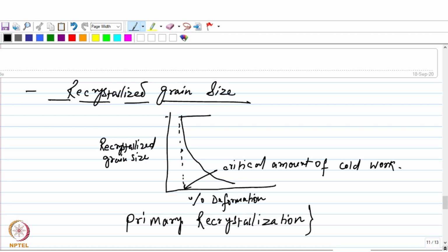But now, once these recrystallized grains have formed, if you continue to heat the material or hold it for a longer time, then what is going to happen? So there is still enough driving force for the boundaries to move and the grains to grow, because it will still try to reduce the surface energy in an effort to reduce the energy of the system, right? So that can only occur when the number of grains reduces and the grain boundary area decreases. Okay, so this is the driving force for the grain growth to occur.